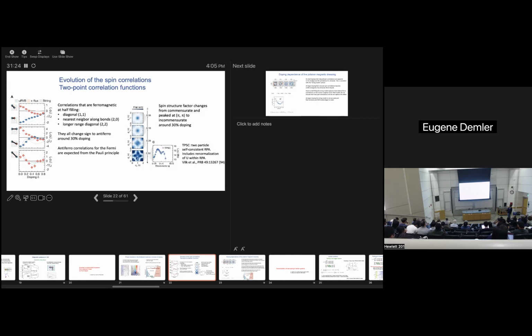Then they take sites which are separated by two lattice constants, but still they're chosen in such a way that in the antiferromagnetic Mott state, they would be ferromagnetically correlated with each other. And then they start changing doping, and they see that this correlation, which used to be ferromagnetic, changes to antiferromagnetic with doping. So then even longer range correlations, but such that they're ferromagnetic at half filling, but with doping, they become antiferromagnetic. And this all happens at roughly a doping of around 30%.